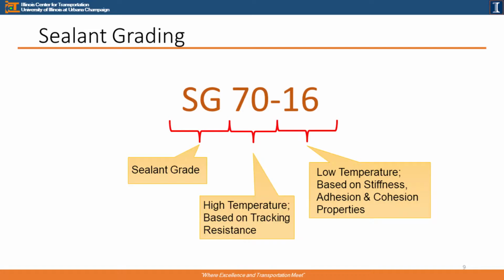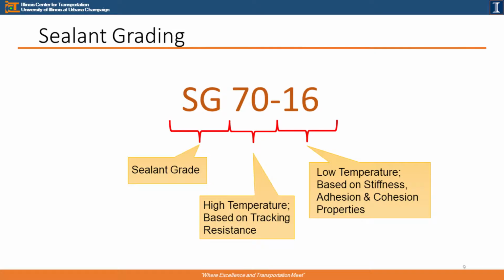So you can refer to these two specifications and practices for more detail. Interesting part. Probably this is the most important slide you are looking at. Okay? Some of you already say, wow, that looks like a PG grading system. Yes, indeed. Okay? What they did was, instead of PG, they call it SG. So what does SG mean? As you can imagine, sealant grade. And then, like a PG grading system, 70 is the high temperature grading. Minus 16 is the low temperature grading. So if you are familiar with the PG grading system, it's a piece of cake. You can easily understand what they did.